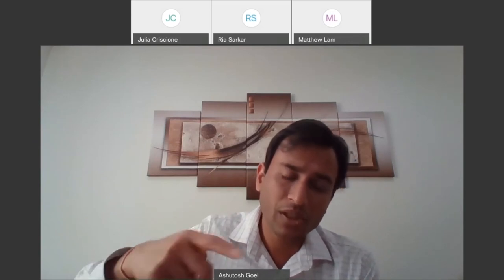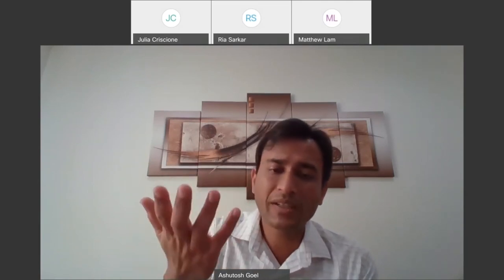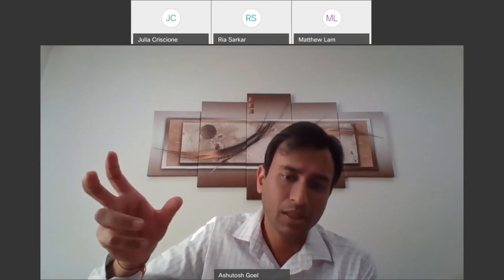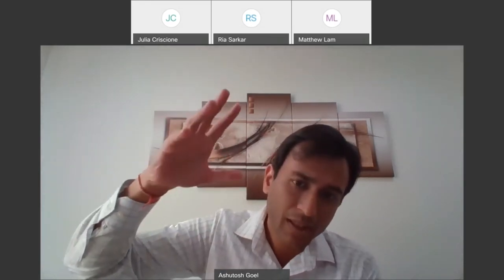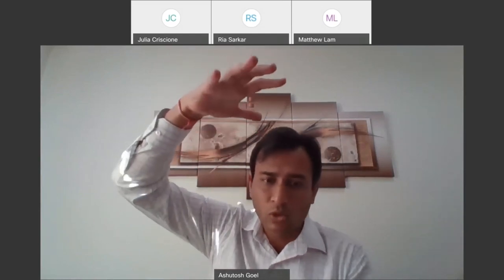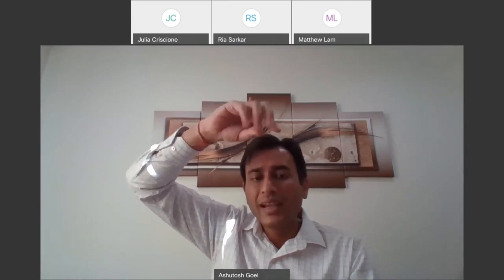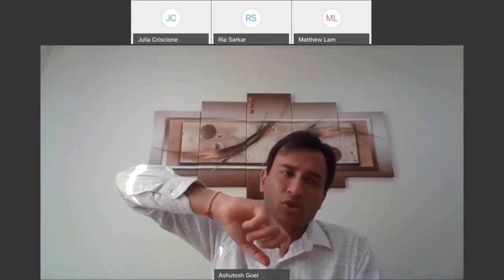What scientists or engineers do when they're melting this waste to convert it to glass is this: upon heat treatment, iodine, for example, I'm just giving you one example. We have more such notorious radioactive species, and iodine is just one example. Iodine tends to leave the melt. It volatilizes from the glass melt. So to capture that volatilized gas, they have got something on top of the melt, a porous bed called a scrubber. It contains soda in it, let's say alkali, or sodium hydroxide.